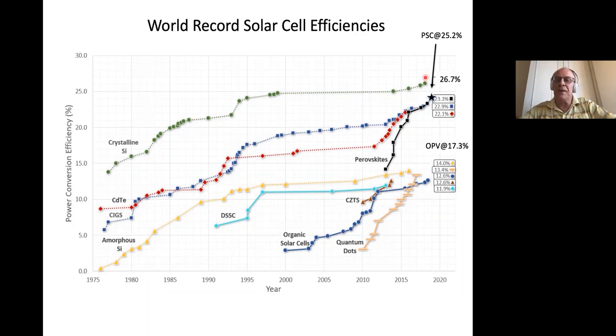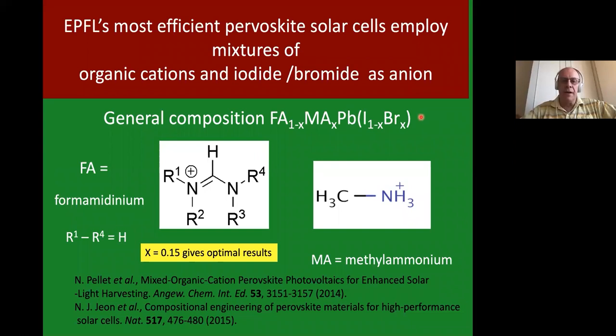The next in line is gallium arsenide, which is at around 29% efficiency. So perovskite has really, in the short term, made it to the top of the world in terms of world record efficiency in photovoltaics. And it's made in a normal chemistry lab, let's say by solution processing, whereas silicon has to be made in expensive vacuum machines and so on. So that's the excitement. I come now to a little bit on EPFL research. This is a starting point to work on mixtures of the composition. As you see here, you can mix in other halides than iodide. You can take bromide. It stabilizes the composition and makes higher quality morphology. It shifts the band gap in a way we don't want for a single cell.